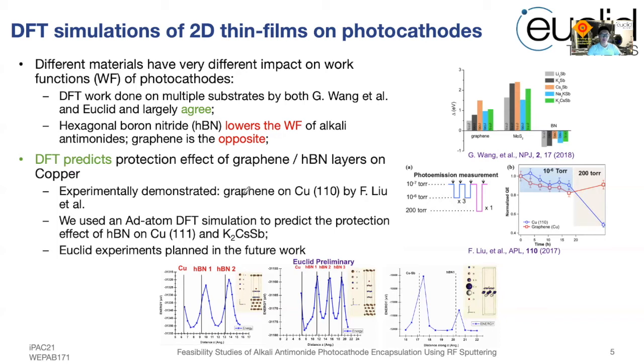Also, independently, we did some DFT simulations to predict the protection effect, for which the work was experimentally demonstrated by a group led by Dr. Liu. And this work was published in APL in 2017. Basically, they had shown that in air, if you have a graphene-covered copper single crystal (110) structure, the QE can be preserved.